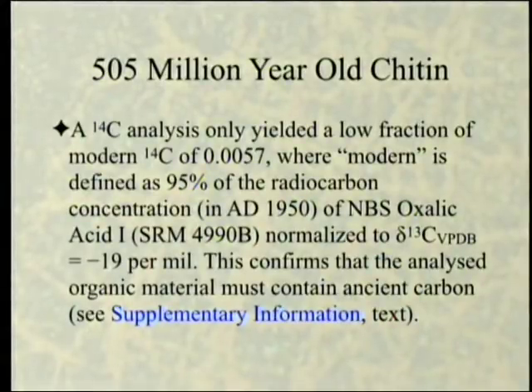A carbon-14 analysis only yielded a low fraction of modern carbon of 0.0057. What does that mean? They'll talk about where modern is defined as 95% of the radiocarbon of NBS oxalic acid normalized to delta 13 carbon of PDB, belemnite stuff, that's minus 19. And this confirms that the analyzed organic material must contain ancient carbon.